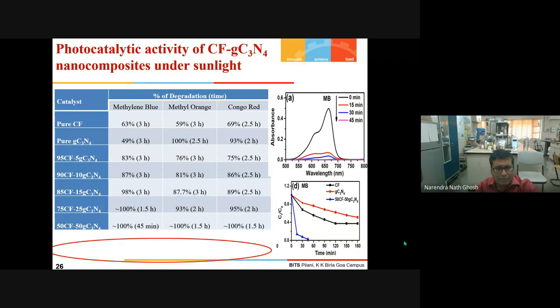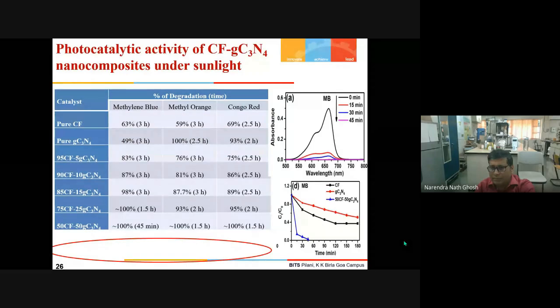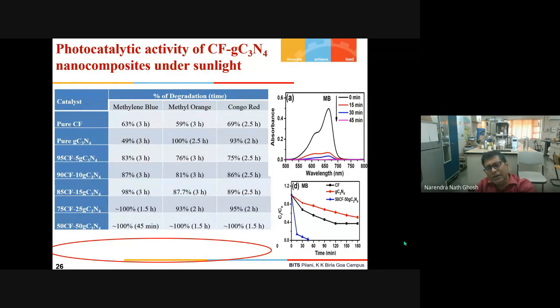I'm sorry, the slide is a little distorted. Here we have seen that the 50% cobalt ferrite and 50% graphitic carbon nitride composition shows the best property, almost 100, I would say 99.99% decomposition is happening within 45 minutes in the case of methylene blue, 90 minutes for methyl orange, and 90 minutes for Congo red.